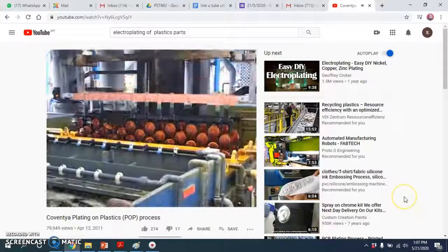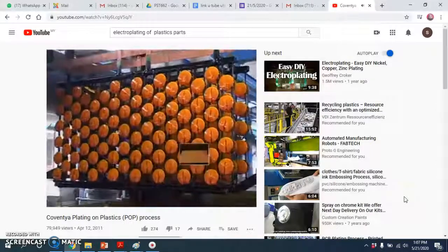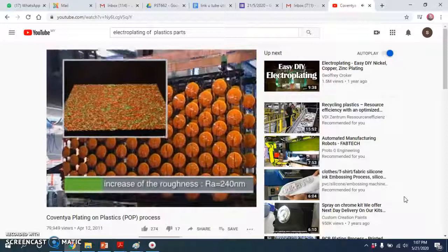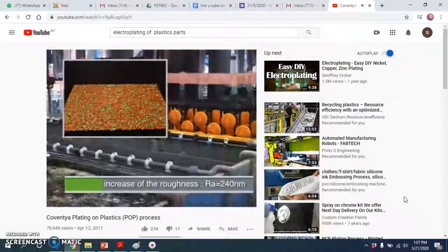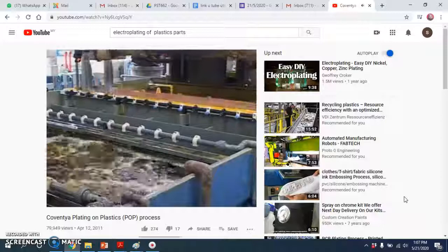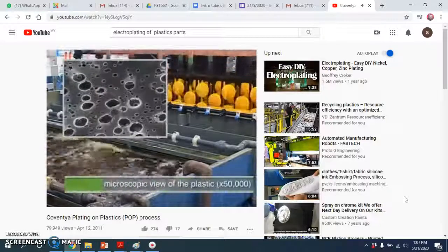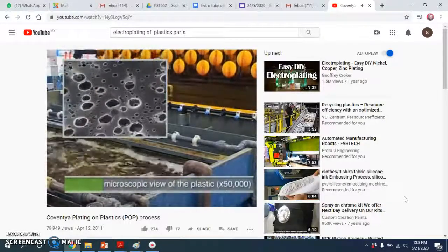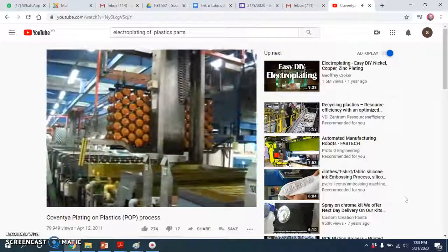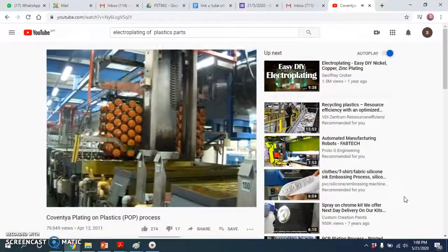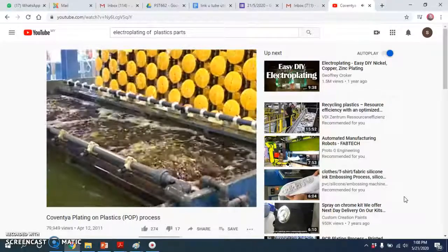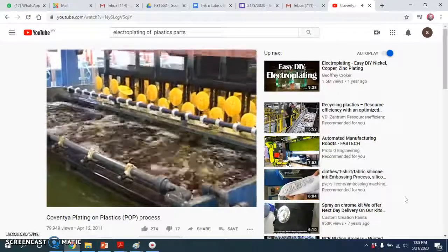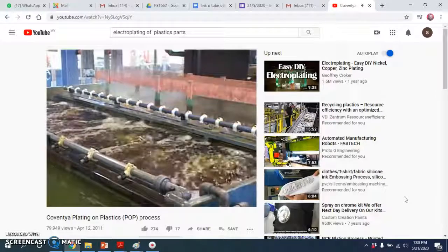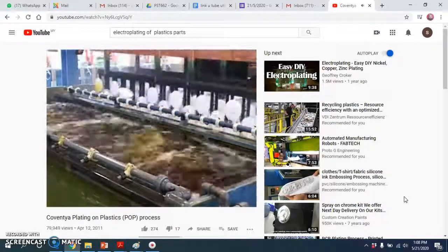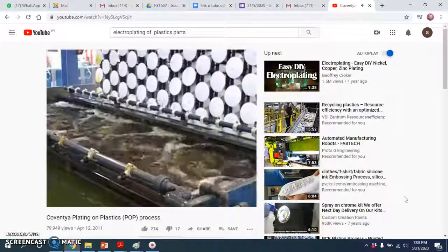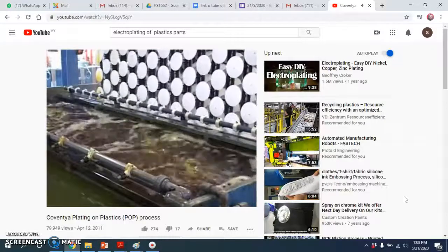Used at 60 degrees Celsius. The etching process is designed to increase the micro roughness of the plastic surface. The topography is roughened to 240 nanometers by creating pores in the plastic, as shown in the SEM photomicrograph. Pores ensure good mechanical adhesion of the layers of copper, nickel, and chromium deposited later in the process. After etching, parts are thoroughly rinsed with water, then neutralized in a chemical step that converts hexavalent chromium to trivalent chromium, since traces of the former will poison the catalytic process.